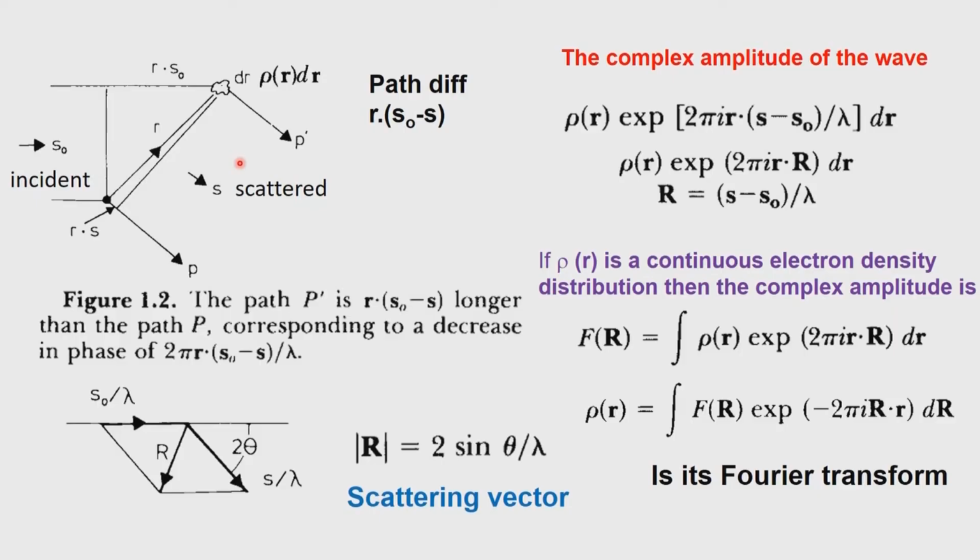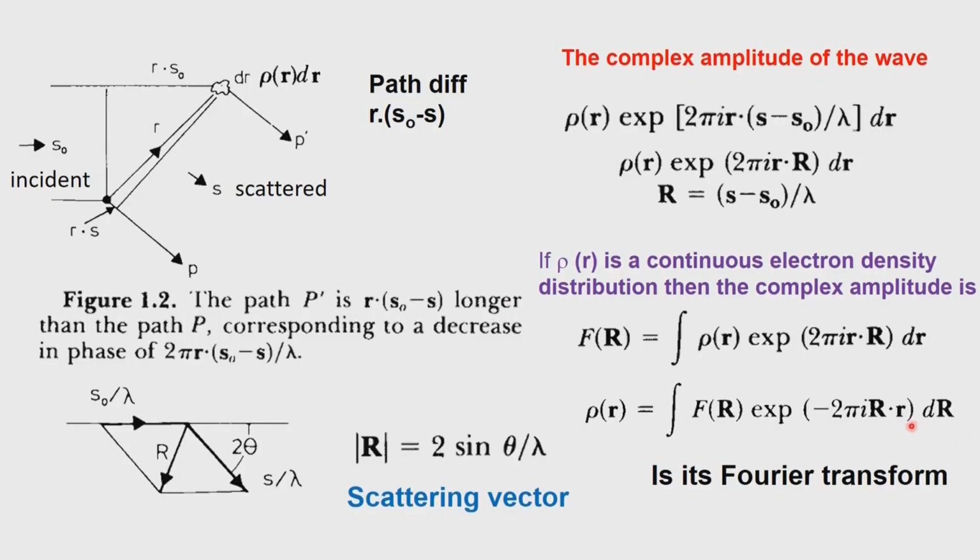So, here the assumption is that atoms are spherical, number one, and they remain spherical even inside the crystal, even after they become parts of the molecule, and these molecules now go in and sit in the unit cell. Under these circumstances, we are making a very serious approximation, because we are neglecting the chemistry of the whole situation. The atoms are not going to be spherical in a molecule, because they get deformed, but we are saying that the deformation is so small. As a first approximation, we can still use these two equations to get to the final structure. Okay. At this time, we can stop.